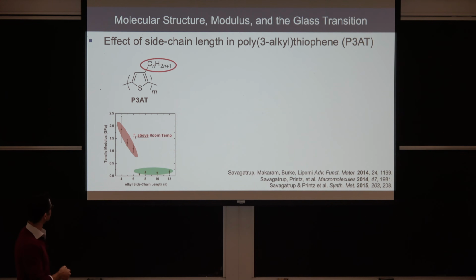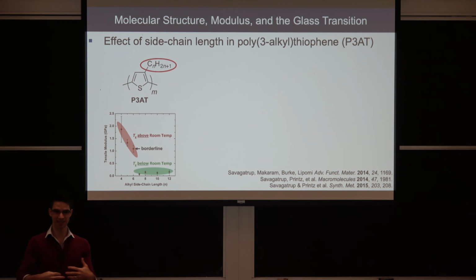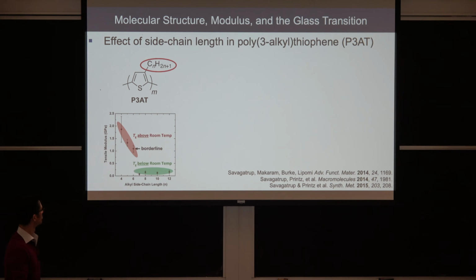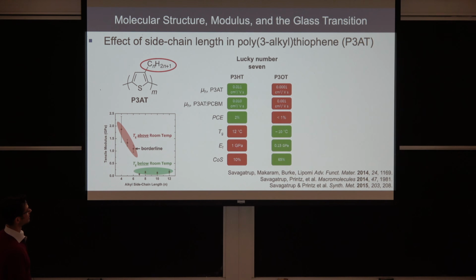And the reason is the glass transition temperature of these materials is above room temperature, so these are glassy, they're stiff at room temperature, whereas these ones are rubbery. Sometimes you'll see C6 have a different Tg depending on what paper you look at, but it's around the borderline. In this particular case, it tended to be glassy at the temperature at which we did the experiment.